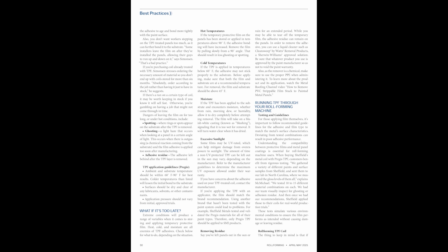Dangers of leaving the film on for too long or under hot conditions include spotting, where rings or spots appear on the substrate after the TPF is removed; ghosting, a light haze that occurs when looking at a panel in a certain angle of light. This occurs when there is outgassing, a chemical reaction coming from the substrate, and the film adhesive is applied too soon after manufacturing; and adhesive residue, the adhesive left behind after the TPF layer is removed.